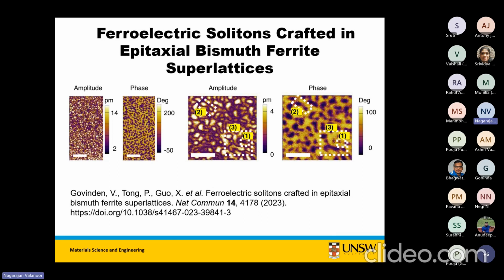So one of the referees asked this question: why is it that the PTO STO guys see very clean vortices or skyrmions? They don't see this kind of mishmash of structures. Why is it that you see it? And we believe the answer lies in the parent ferroelectric. The parent ferroelectric, lead titanate, has one stable polarization orientation and 6 variants at the most. Bismuth ferrite has 8 variants, so it has all the more degrees of freedom compared to lead titanate. I think that's one of the reasons why it forms all these different kinds of topologies.